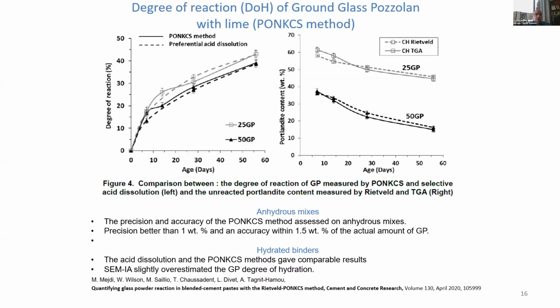Now, the degree of hydration, of course, we use the ASTM method, and we also use the lime method. But here we use the PONKCS method by XRD of amorphous material, and it works very well. It works very well for glass. Maybe it doesn't work for some other pozzolanic materials, but for glass, we definitely can use the PONKCS method, and it gives excellent results. We can see here that at 25 or 50% replacement, we have very good reactivity, and you can go to these papers here in Cement and Concrete Research. We published all this.